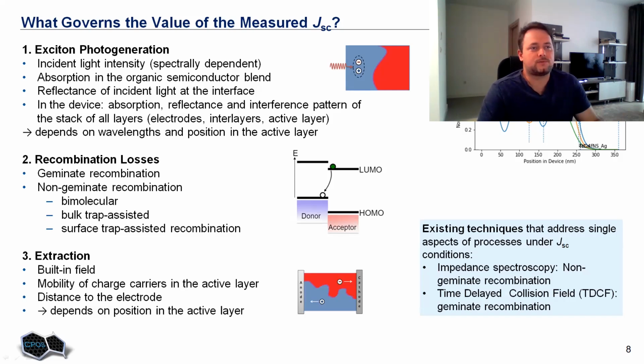For instance, here is shown for some device stack. Here is our active layer and interference picture for different wavelengths. So we definitely need to do it for all wavelengths of the solar spectrum and consider what part of these wavelengths will be absorbed, where these excitons will be generated. That will give us information on the generation of excitons within the thickness of the active layer. However, this is only the first step, because in real life we have problems, and that comes with recombination.